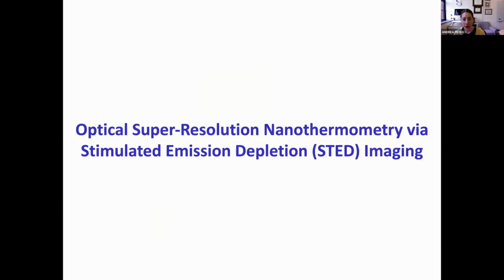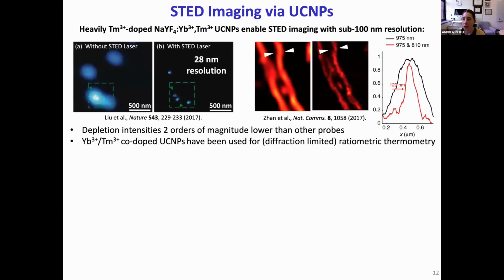So I'll now transition into my group's work on developing the first super resolution nanothermometry technique, starting with some of the more recent advances that paved the way for our work in this area. As I mentioned, STED has traditionally relied on organic dyes and fluorescent proteins, but in 2017, two different groups both reported the first demonstrations of STED imaging using upconverting nanoparticles, UCNPs, which again is the same class of nanoparticles that we've used for ratiometric thermometry. Specifically, both these groups showed that sodium yttrium fluoride UCNPs doped with ytterbium and a much higher concentration of thulium than had been used before enable STED imaging with resolution down to about 28 nanometers.